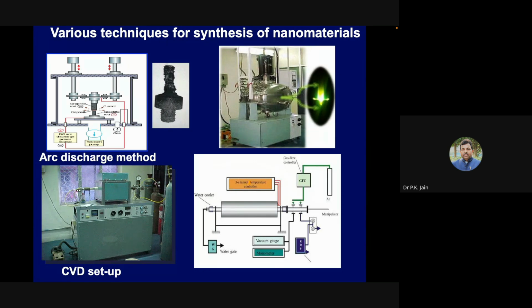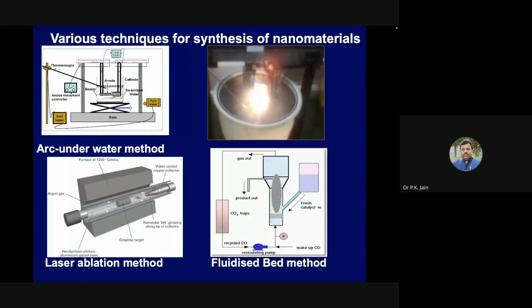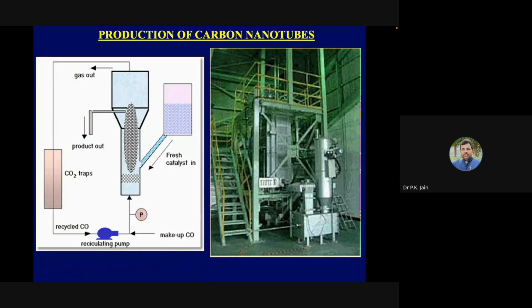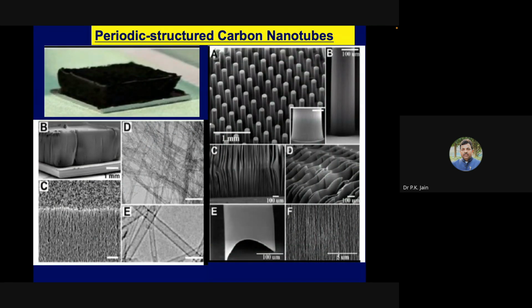These are the few setups that we have in the center. The arc discharge, where two graphite electrodes are kept and a very high current is passed at a specific voltage, and you will get a deposit, and this deposit will have a lot of carbon nanotubes. We have chemical vapor deposition. This is another setup, arc underwater, laser ablation setup, and the fluidized bed reactor. Commercially, the fluidized bed reactor is very popular because you can produce carbon nanotubes in tons. However, CVD is also used for making different types of functional requirements, whether it is a pillar or the flakes or everything. You can design your catalyst and other things, which is possible.